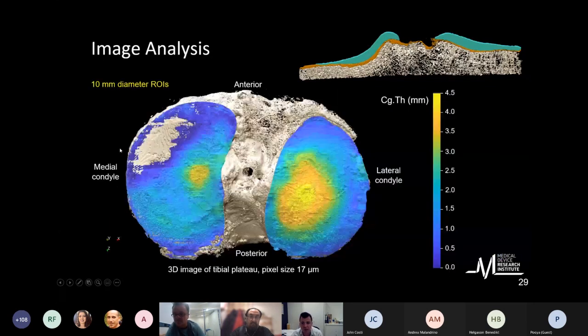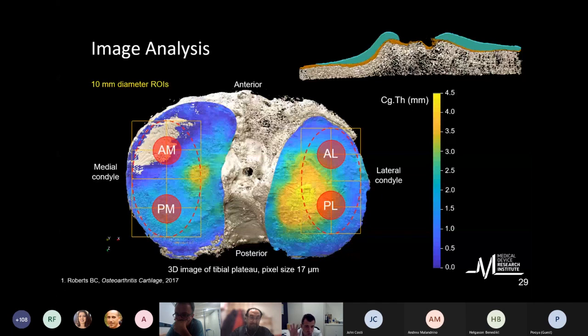And this is a mapping of the thickness performed on an excised tibial plateau that is aligned, and you can see the area of the denuded cartilage on the top left, which is anteromedial. Now, we looked at the cartilage in those regions that previously were identified by Brian in his paper as being those that were more relevant for looking at differences in the bone. So we were just looking at the cartilage above in the same regions, in the same patients.